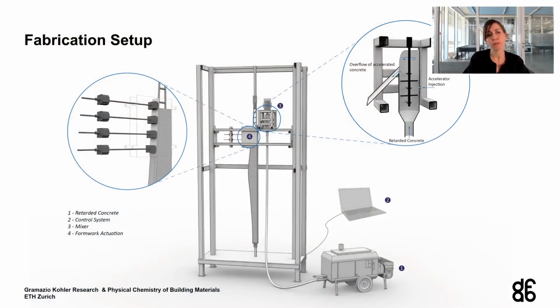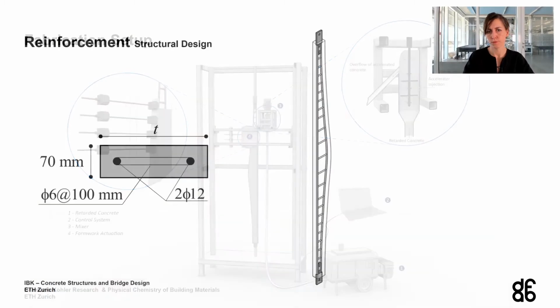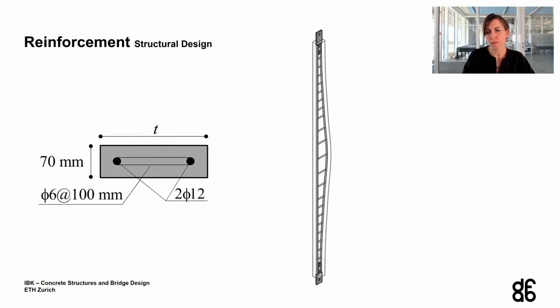The fabrication setup that we used was a linear axis, so no longer the 6-axis robot. For this, we again installed a pump that pumped into our reacting system and our actuated formwork, which all together was synchronized in a custom-made software. The reinforcement was probably one of the biggest challenges and novelties of the mullions, since we had never really implemented that in the SDC process. We also had to reduce the cross-section down to a minimum of 7 by 12 centimeters, which of course posed a number of challenges in terms of friction.